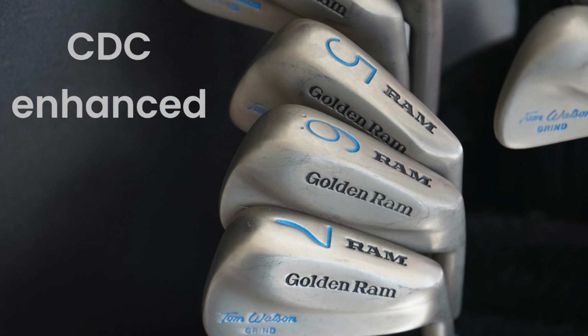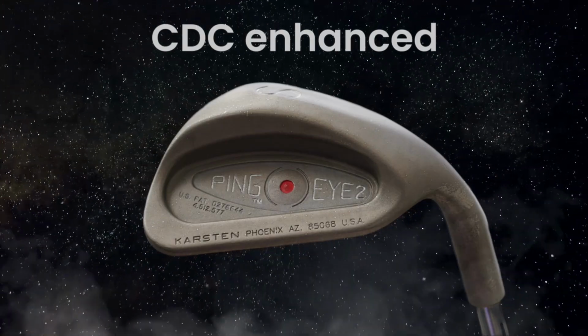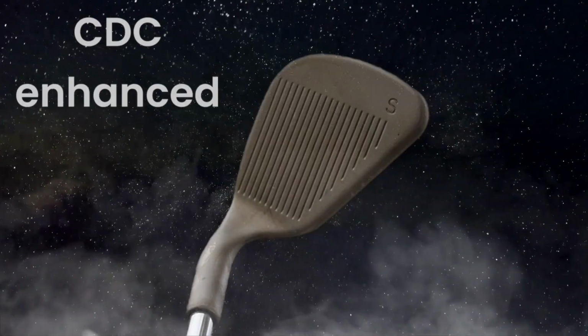So when you're looking at coating woods and irons, the objective is energy transfer. And diamond obviously is the hardest material known to mankind, and we tested this initially with very simple tests. We would take two panels, both the same steel, but one with our diamond coating and one not, and under time-lapse photography, we measured the rebound height of golf balls off of each of those panels, and we saw a 4 to 7% increase in the rebound height of the golf balls coming off of the panels that were enhanced with composite diamond coating.